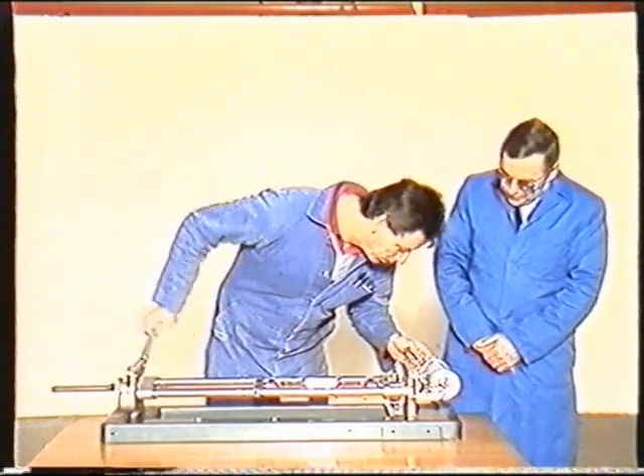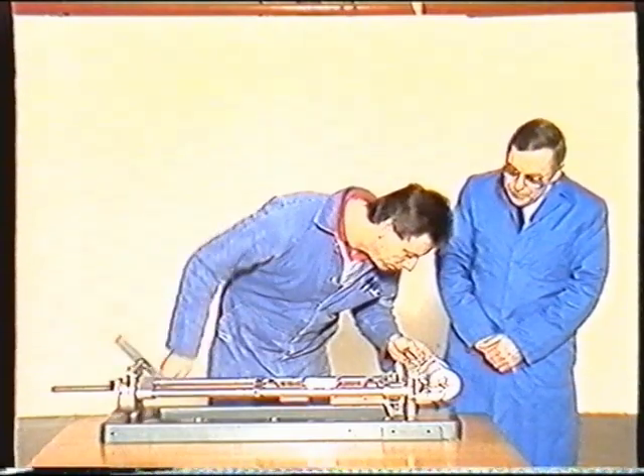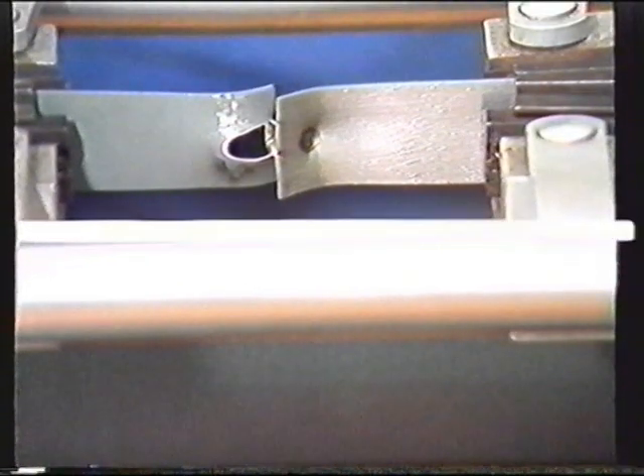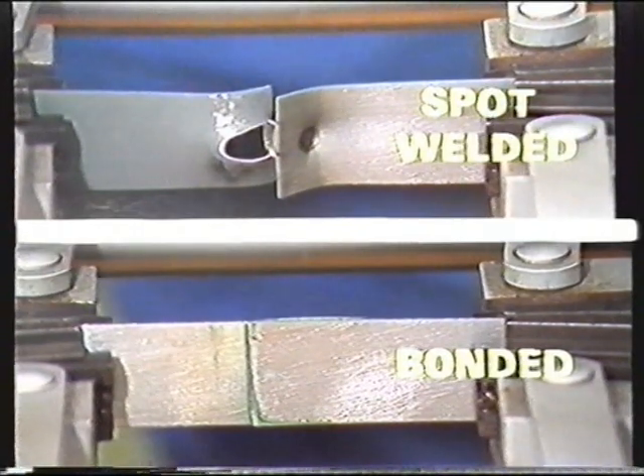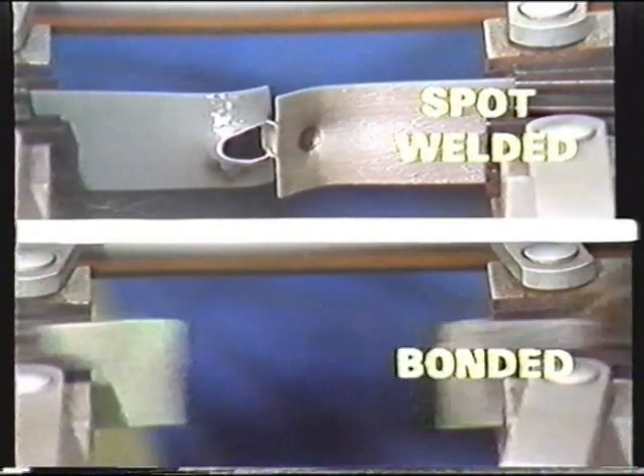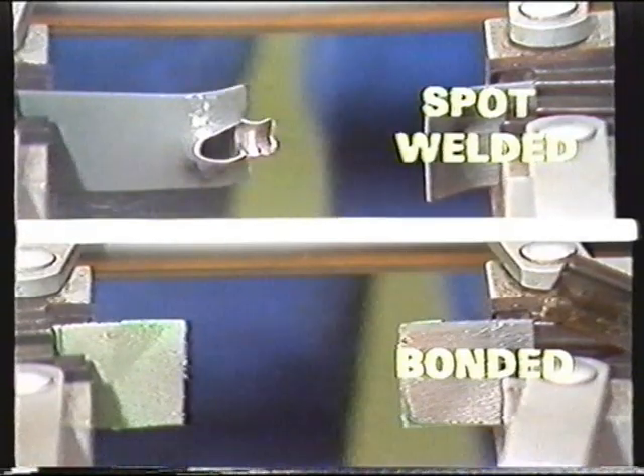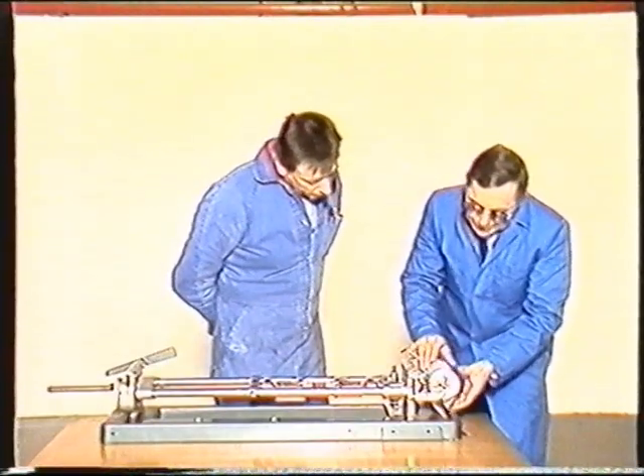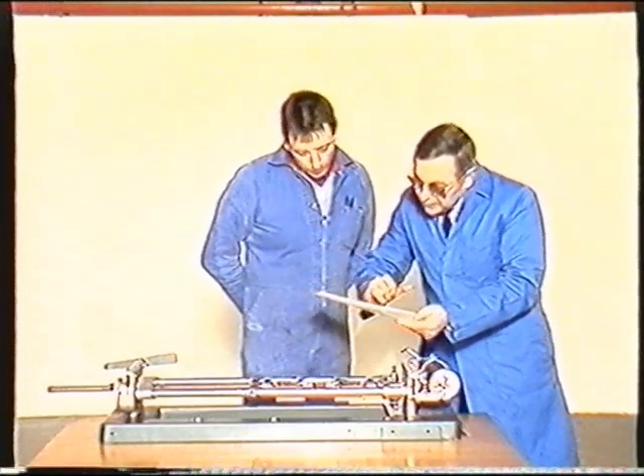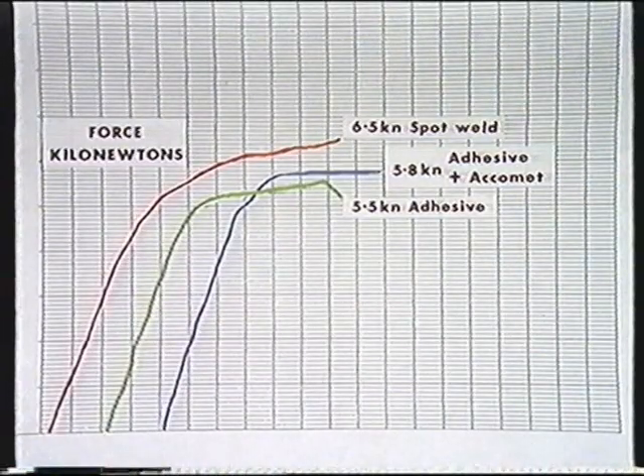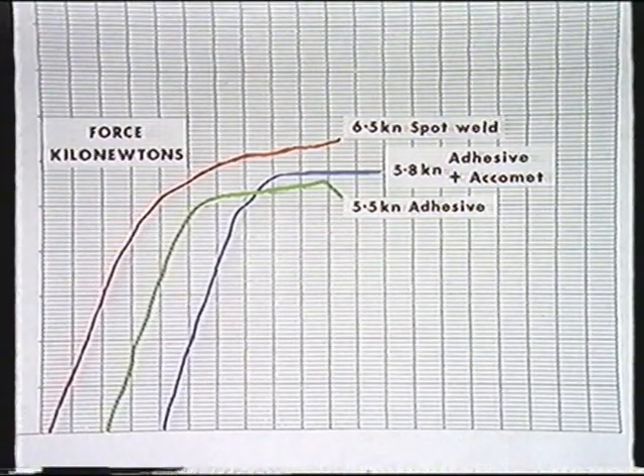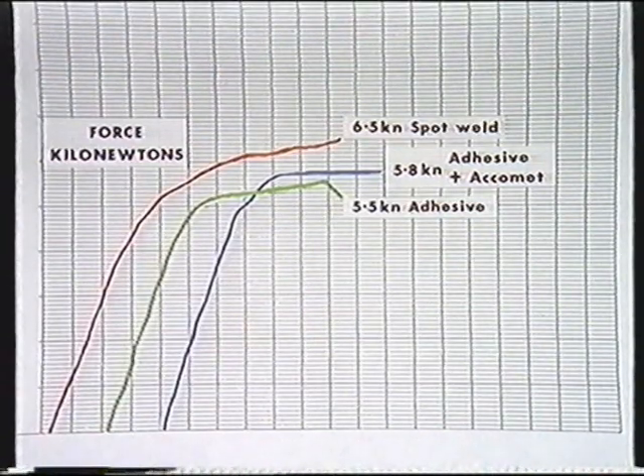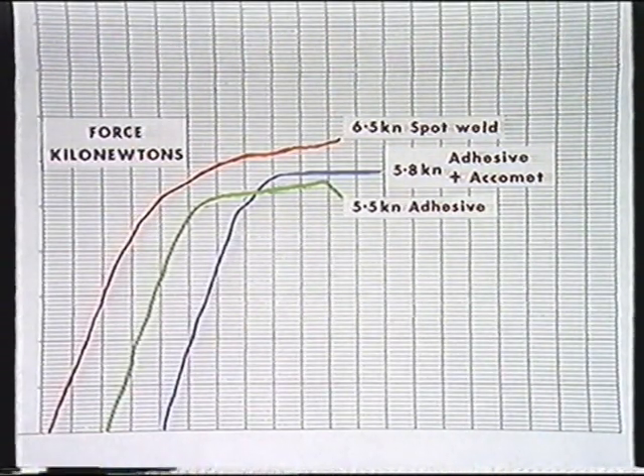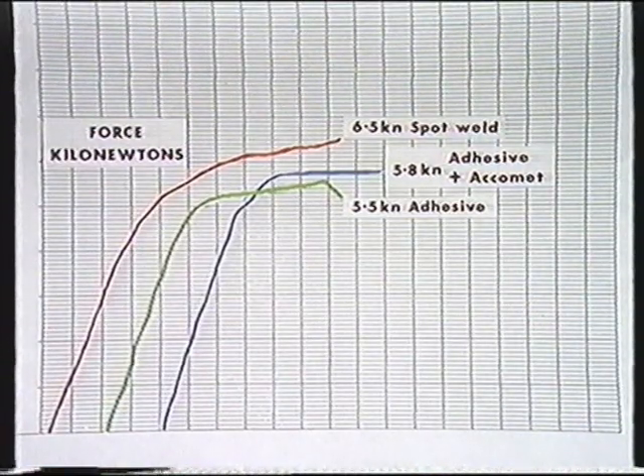To compare bonding against welding, Thatcham conducted tests on a tensometer. At the top is the resistance weld, and at the bottom the bonded joint. The test specimens were made up with 1mm gauge steel. Examination of the graphs produced proves that bonding can be just as effective as spot welding. The spot weld failed at 6.5 kilonewtons and pulled a 5mm nugget. Chemical pre-treatment enhanced the strength of the bonded joint by 0.3 kilonewtons. The real advantage of the Accomet, increased durability, is only realized in service.